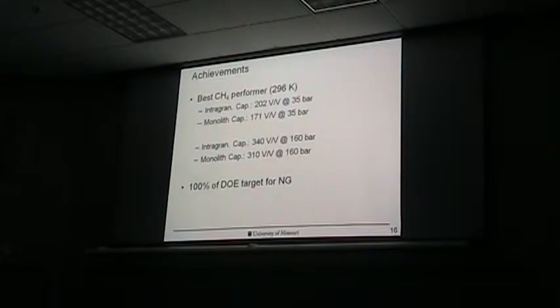To give you some numbers, our best methane performer at room temperature has, at 35 bar, 202 volume over volume. That means volume of gas over the volume of our material. And as monolith, you still have 171. And at 160 bar, it's even 340 volume over volume, or 310. This material is already so good that it is over the DOE target for natural gas storage. So we already fulfilled the DOE target for these materials.